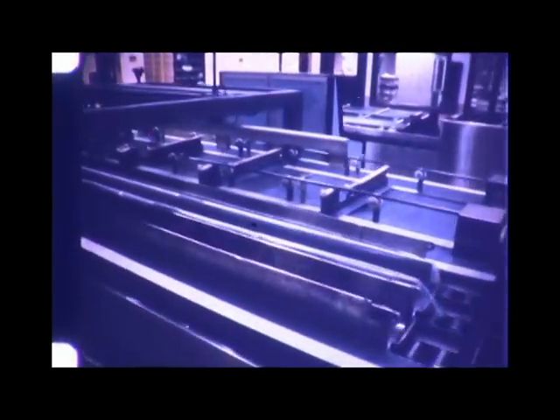Fuel rods are transported along the axis of a superconducting solenoid. Small pickup coils inside the solenoid respond to changes in the magnetic moment of the fuel. Since gadolinia has a higher paramagnetic susceptibility than urania, the gadolinium content of each pellet can be measured. With simultaneous measurement of fuel density, the gadolinium content can be determined to plus or minus 0.4 of a weight percent for each pellet and to plus or minus 0.2 of a weight percent for zone averages.